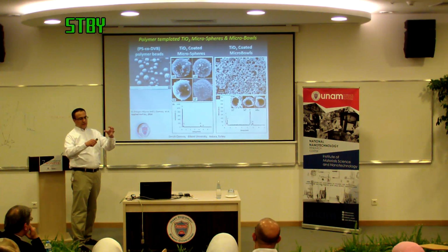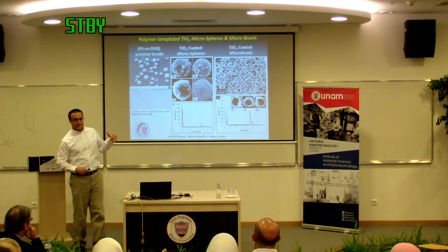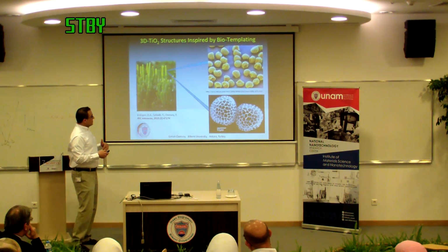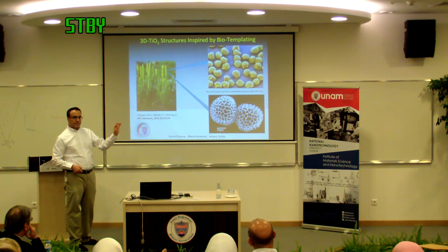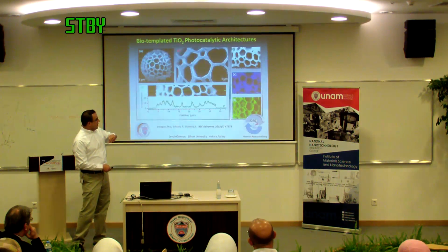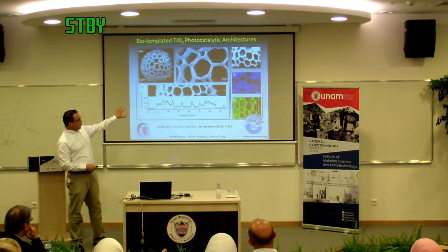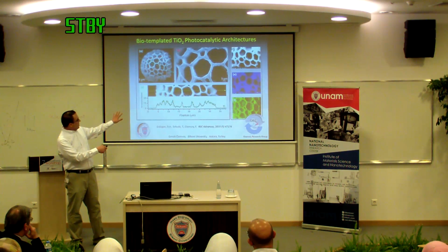The idea is like, can you have some light, the kind of confinement? Can you do more chemistry inside the cavity? Doesn't work that well, but it's okay. Nowadays, we have been using some interesting materials. So these are pollen spores, which are about 10 microns in size. They have brilliantly nice, pretty structures, very difficult to synthesize. These are cellulosic materials, and you can coat them with titanium, burn off the cellulosic material, and you end up with this interesting titanium structure.